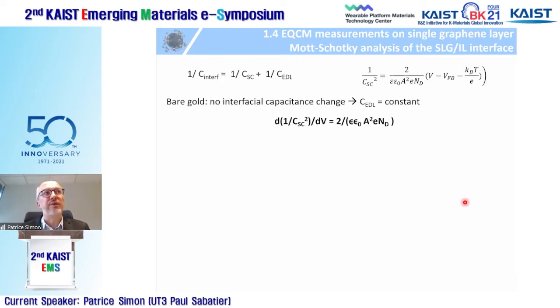And then what we did, to try to go a little bit further, we did a Mott-Schottky analysis of this single layer graphene ionic liquid interface. So the interfacial capacitance is the sum of a space charge capacitance, as we can call it, and the double layer capacitance, space charge from graphene and double layer from the material of the gold. As we saw before, this double layer capacitance is constant. The gold capacitance is flat with potential. And the space charge capacitance is given by the Mott-Schottky equation, 1 divided by C squared is proportional to the delta V, V minus VFB being the flat band potential. It's proportional to the increase of potential versus the flat band potential.